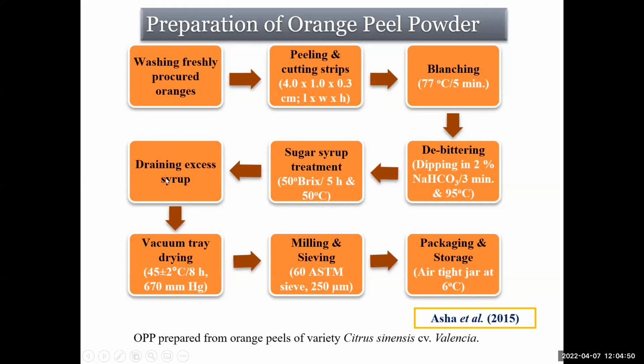After that, just drain the excess sugar syrup. Then vacuum tray drying at 45 plus or minus 2 degrees Celsius for 8 to 10 hours, depending on the final moisture, which should be less than 8%. After that, milling and sieving is done, and the orange peel powder with 7 to 8% moisture is packed in an airtight jar and stored below 6 degrees Celsius.